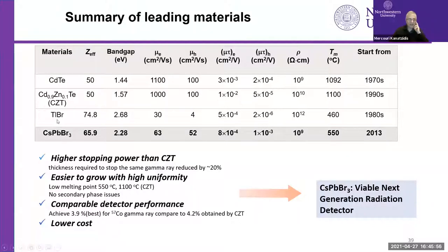So there are not that many. One is cadmium telluride, which is the parent of cadmium zinc telluride, the parent of CZT. What's wrong with cadmium telluride? The band gap is too low, 1.44. It has very good mobilities for electrons, very good mu taus, but reasonably low resistivity and high melting point. This is good for X-ray detection, but not for gamma ray detection.